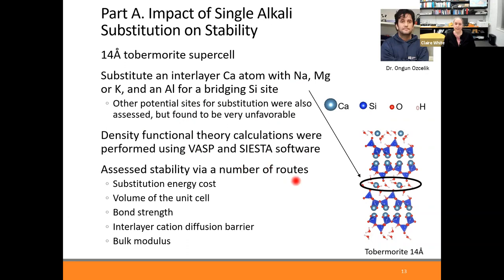And from these calculations, we can get a variety of properties of the crystal, such as what's the substitution energy cost when you replace, say, a calcium for a sodium? Does that change the overall volume of the system? Does it change bond strength? Can the cations diffuse around more easily? And there's other properties as well.